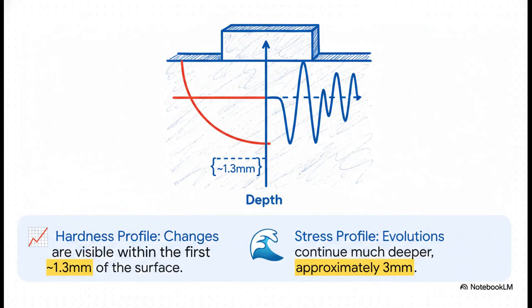And this slide just illustrates the point perfectly. Look at the left. You see that hardness profile we saw before? The hardness is high and stays pretty steady near the surface, maybe in the first millimeter or so, before it starts to drop. But now look at the stress profile. It's telling a totally different story. While the hardness is changing over about, say, 1.3 millimeters, the stress, man, that keeps evolving way, way deeper, sometimes down to 3 millimeters. A test that only looks near the surface is completely blind to what's happening underneath.